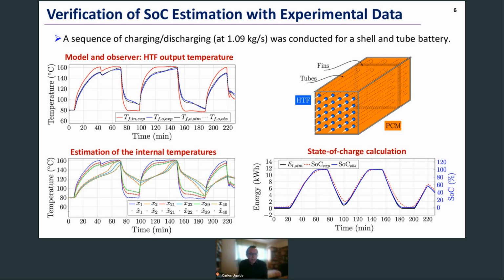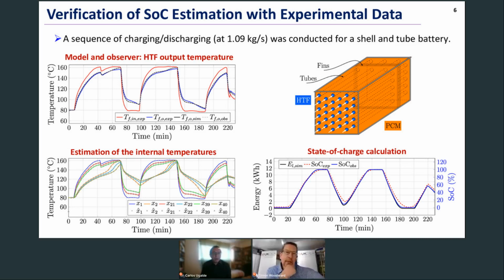This, I would like to highlight, is experimental data. If this input profile is fed into the model, it can be seen that the simulated output temperature, which in the graph is given with a black trace, is similar to the real one. This demonstrates the accuracy of the thermal battery model. However, more importantly, the temperature estimated by the observer, given with a dashed line, matches very well with the output of the simulation. The bottom graph shows the performance of the observer, where we can see the estimated temperatures. This is provided by the observer without the need for internal sensors.